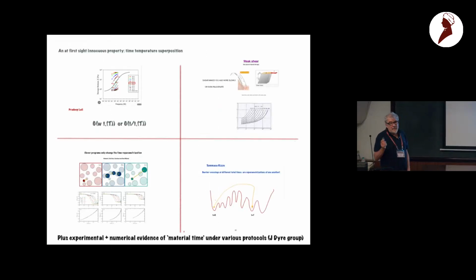Okay, so let me tell you examples where this appears and you confirm that it's the way it works. I told you already this case, a very famous case that was noted by Struik many, many years ago: if you take a ruler and you do aging of the ruler, so you stretch it and see how it creeps, it ages, so these are curves for different times. But if you take your ruler and every weekend you do this to the ruler, then it stays young. It does exactly the same, but the time scale at which it does it is that of a younger system. Younger systems have the same correlations, but do the same things faster, and then progressively things become slower. This is aging, but you can stop aging very easily just by shearing your plastic ruler. And this has been checked, but this, I think, was discovered by him many, many decades ago.